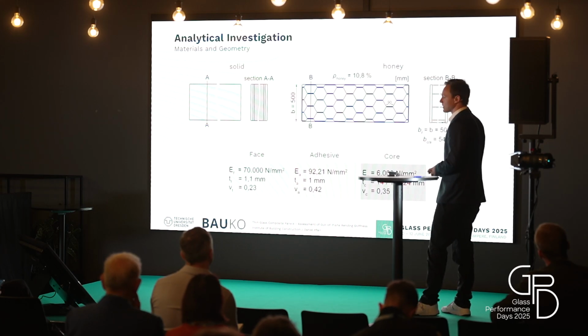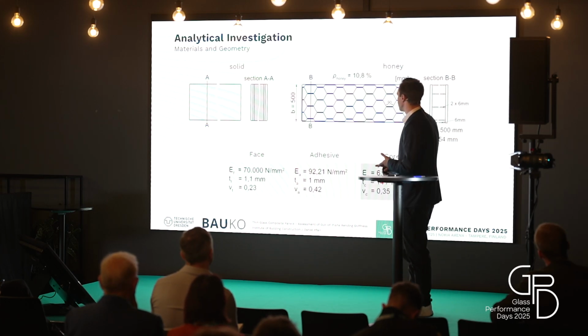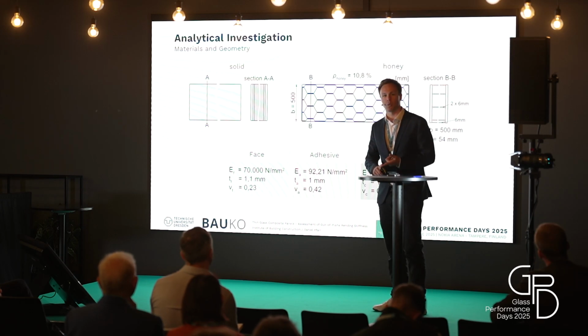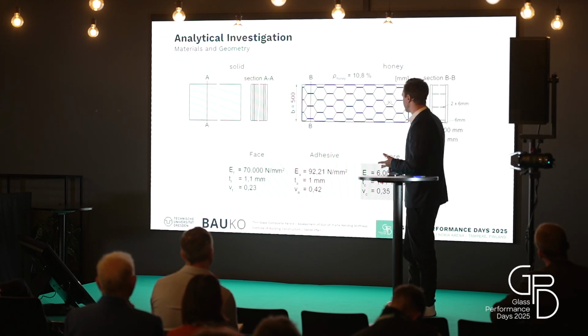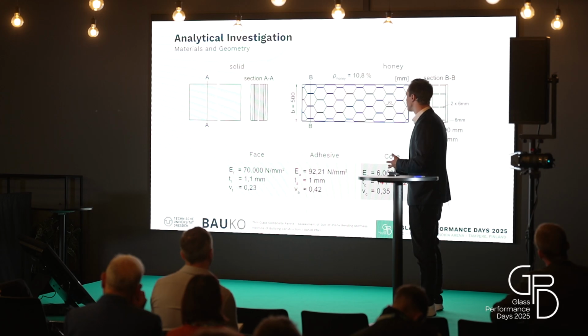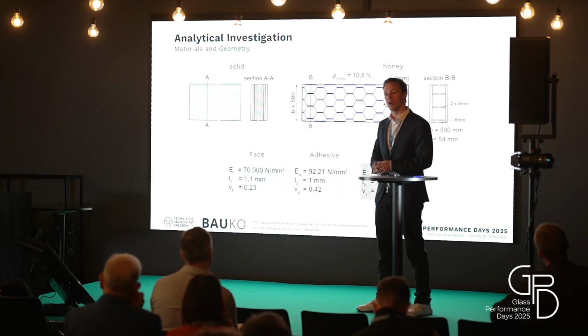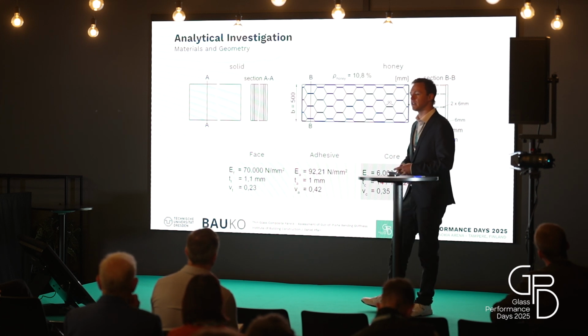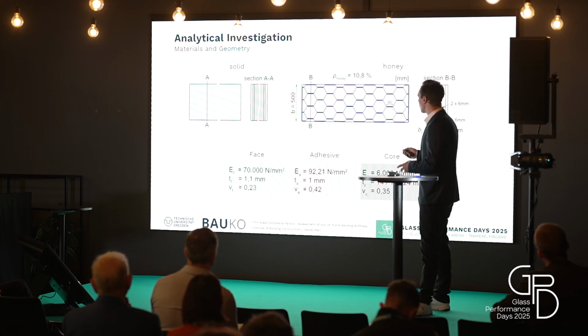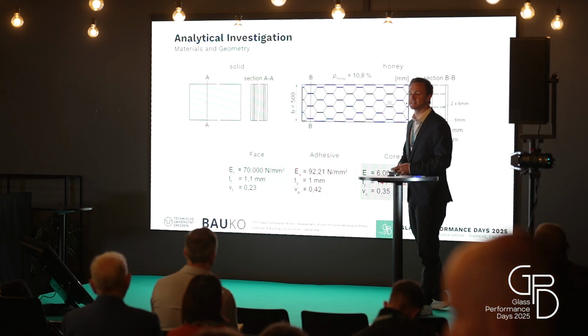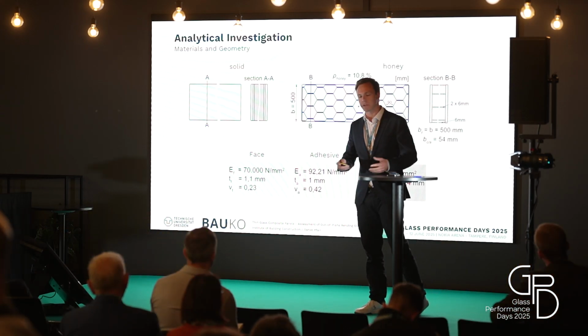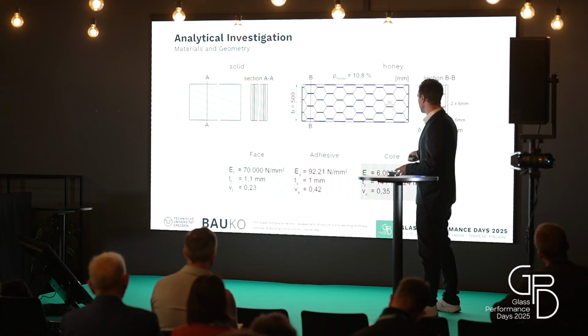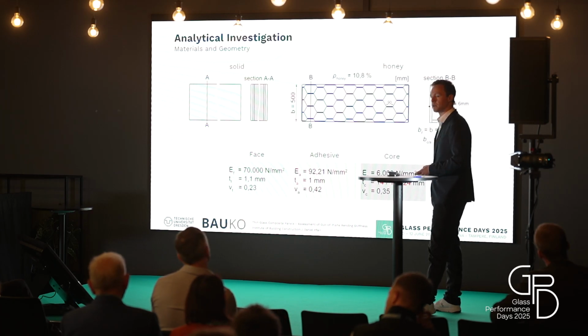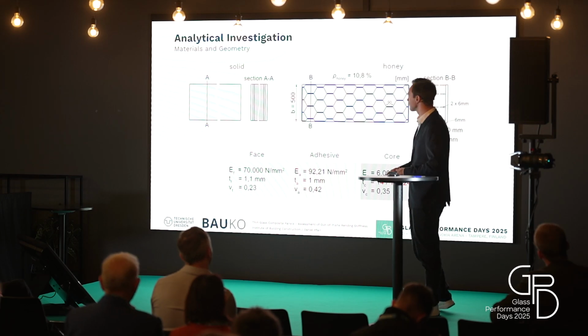We have some materials used, 3 different components. So we have the face, which is a thin glass, 1.1 millimeters thick. We have the adhesive, which is around 1 millimeter thick as well. In that case, it is a polypropylene-based hot melt, which has a stiffness of around 90 Newton per square millimeter. And the core with a stiffness of approximately 6,000 Newton per square millimeter, according to the data sheet. And we investigated this with 3 different core thicknesses, 14, 19, and 24 millimeters.